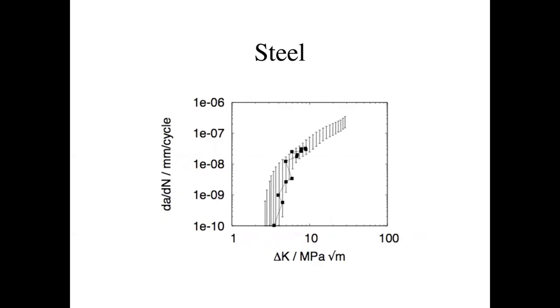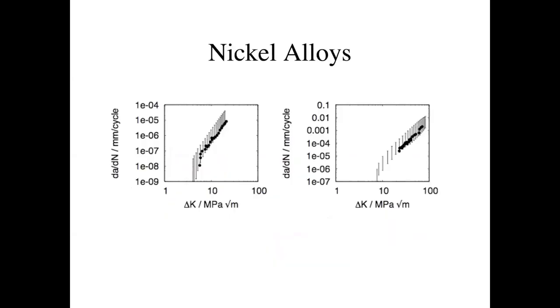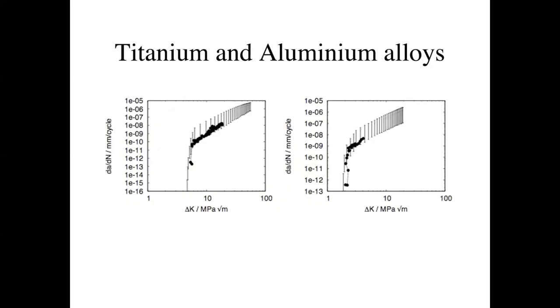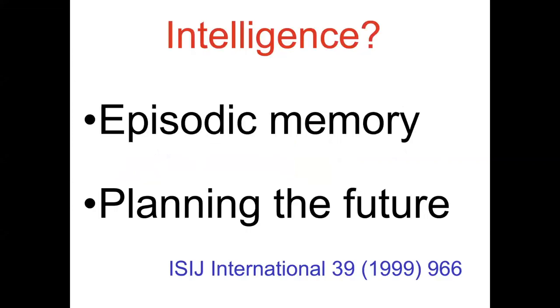And we tried that, and you can see really quite remarkable prediction of fatigue crack growth rate in nickel alloys, even though the database doesn't contain a single nickel alloy. And then we tried aluminum alloys, titanium alloys, and you can see that if you design your model appropriately, it can be of generic value. Okay, so I'm going to stop because I'm running out of time now with this last slide. So I want you to decide whether the method is intelligent or not.